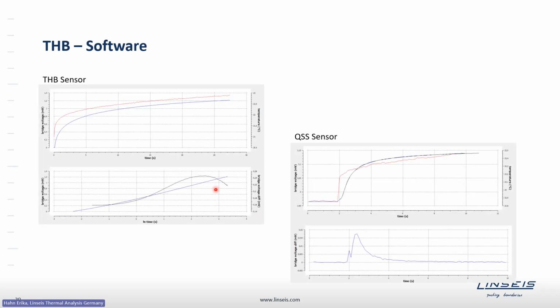Here you see the screenshots of the measurement curves, on the left side of the THB sensor and on the right side of the QSS sensor, where you directly see the curves look completely different. That is just due to the fact that the alignment of the wires within the QSS sensor is different, and also the evaluation is different.